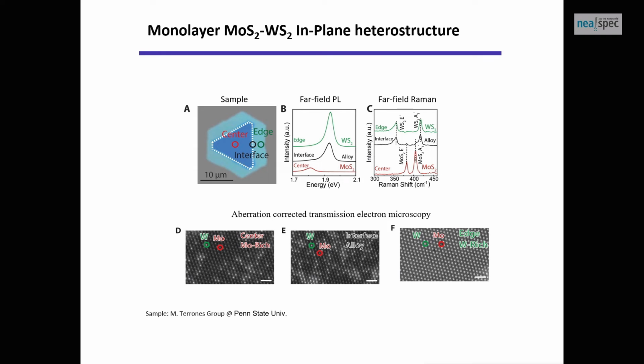So the monolayer looks like this. If you look at it with an optical microscope, what you notice is the color of the outer layer is different from the inner layer because the two are different materials. The outside is WS2, the inside of this material is MoS2, and the two are covalently linked at this interface. And that interface turned out to be very important.